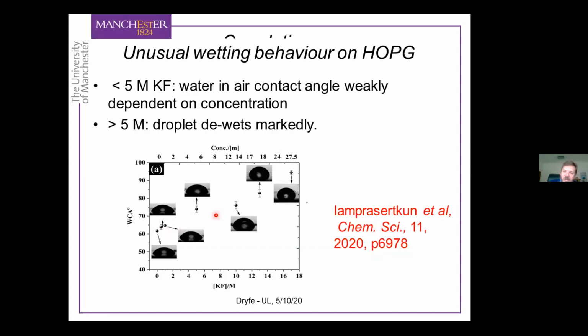If you go to quite high electrolyte concentrations, once you get to 5 molar, you do see a change in contact angle, which is significant, much bigger than experimental error. It does change by 10 or 15 degrees when you get up to 5 or 10 molar. But the weird thing is, when you get to these very high electrolyte concentrations, where basically the ions are closer than the Bjerrum length, you don't have enough water around the ions to solvate them properly. So the ions are interacting with each other in very weird ways, and that means the contact angle changes massively and goes above 90 degrees even at the highest electrolyte concentrations. So basically the droplet de-wets from the graphite surface.